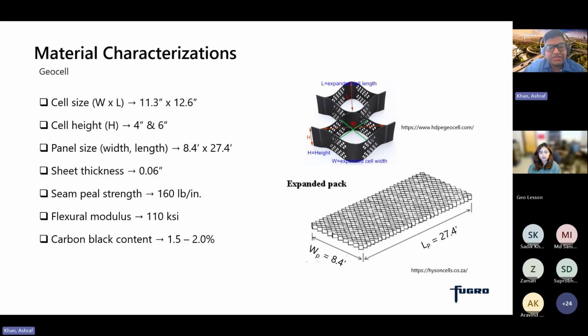It came from the TechStart specification of compaction. When you put the infill material into the Geocell pocket, you need to have at least 2 inch of clear cover on top of the Geocells. So with 6-inch Geocell and 2-inch cover, the maximum lift thickness is 8 inch. And according to TechStart specification, we cannot go beyond 8 inch of lift thickness. So that's why the maximum size of 6 inch can be used for the construction of pavement.